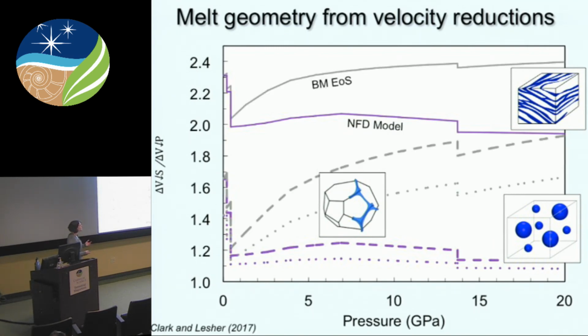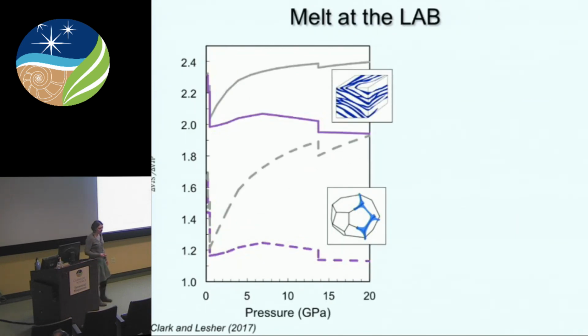In contrast, when we use the Birch-Murnaghan equation of state, we see that there's actually a very strong pressure dependence for this ratio of the S to the P wave velocities. So this means, right, for the network flexibility densification model, the only way to move between these values is to change the geometry. Whereas with the Birch-Murnaghan equation of state, this ratio is dependent not only on melt geometry, but also pressure. Okay, so let's look back at the LAB. Remember I told you that in the Western Pacific, there have been seismic observations that at depths corresponding to the LAB, there's about an 8% velocity reduction for both P and S waves.